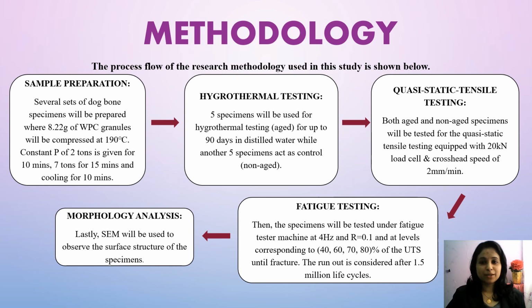Next up is the methodology. The process flow of the research methodology used in this study is as shown below. First, sample preparation. Several sets of dog bone specimens will be prepared, where 8.22 grams of WPC granules will be compressed at 190 degrees Celsius. Constant pressure of 2 tons is given for 10 minutes, 7 tons for 15 minutes, and cooling for 10 minutes. Then, hygrothermal testing.